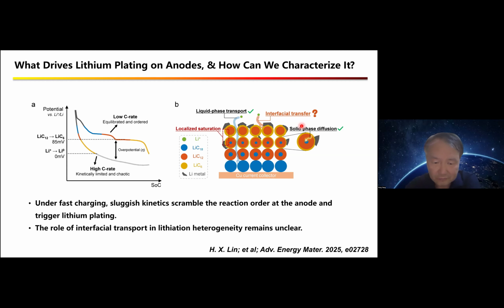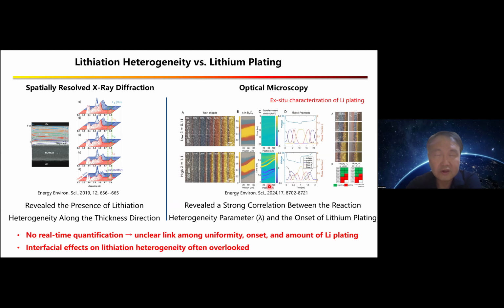In this work we try to distinguish these and give evidence to understand this, because determining the amount of lithium plating has been done in the literature, but it's more difficult to determine which factors determine lithium plating and lithiation heterogeneity against lithium plating. I think this is quite difficult.